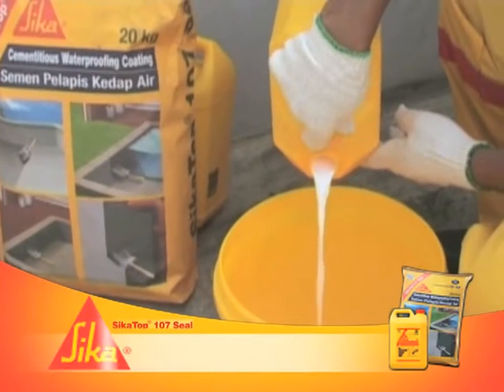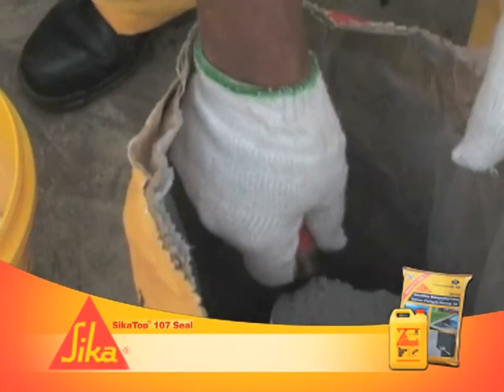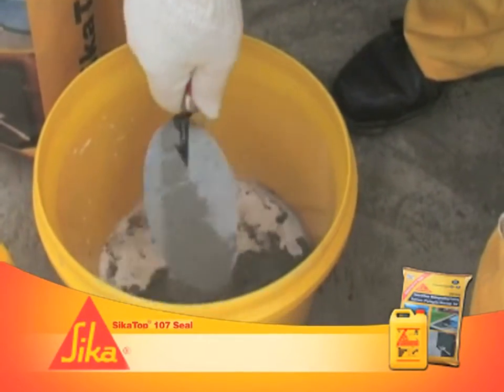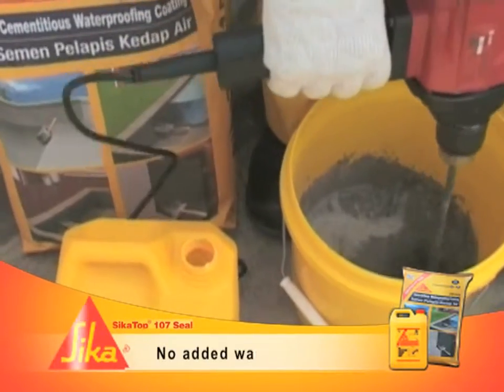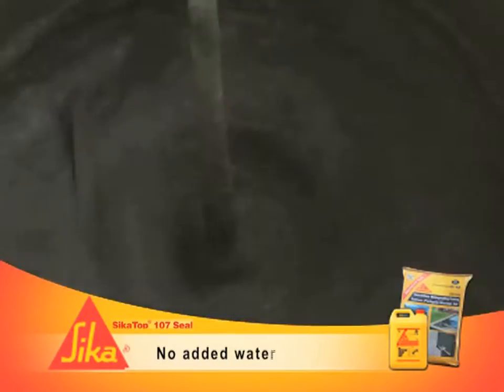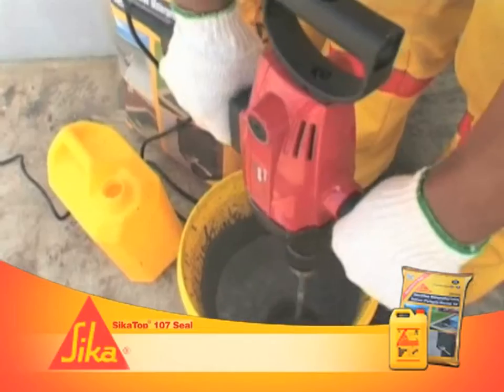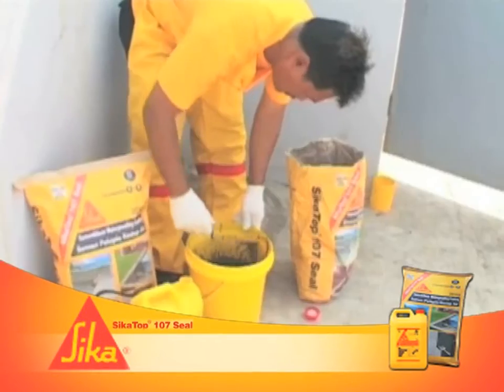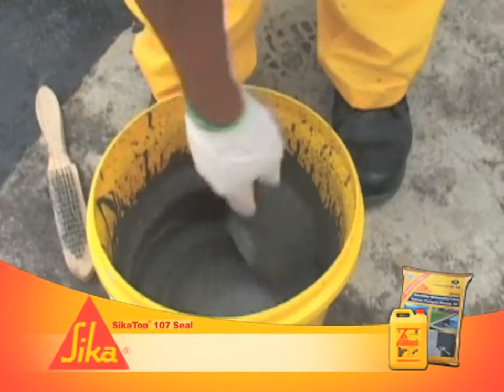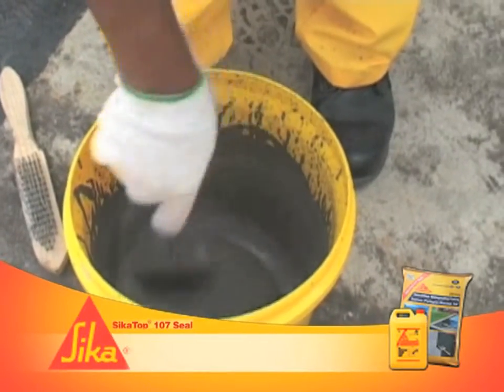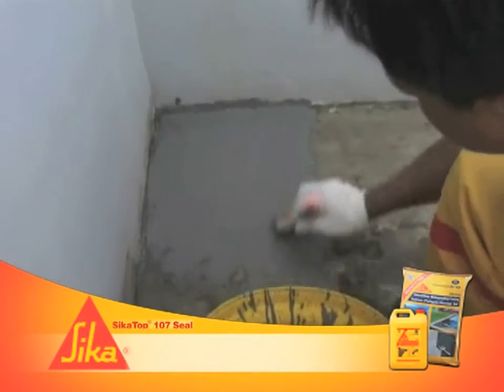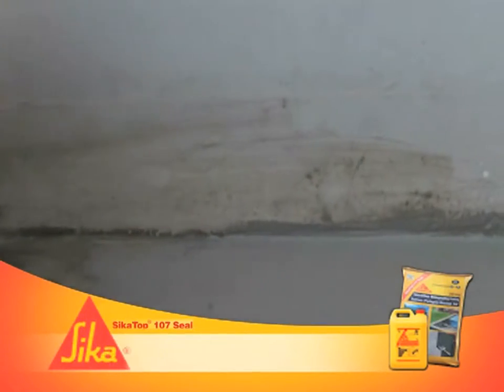Pour half of part A into a clean container. Add all of part B in a powder form. Mix thoroughly with a low-speed mixer. Add the balance of part A into the mixture and mix for 3 to 4 minutes. Apply the mixed SikaTop 107 Seal with a brush or trowel. For large roof areas, protect the surface with boards of 2 to 3 centimeters thickness.